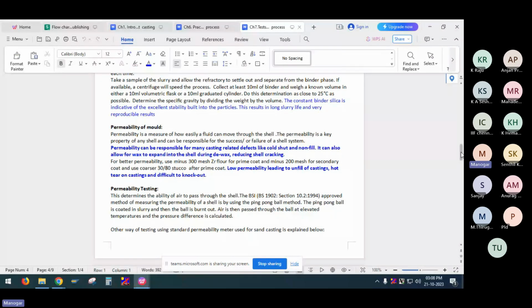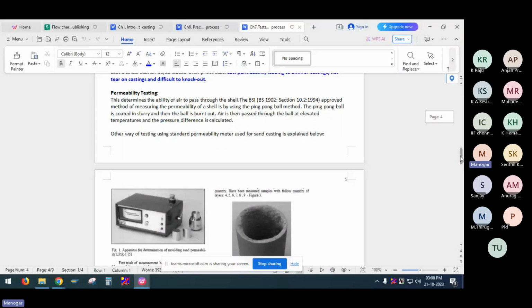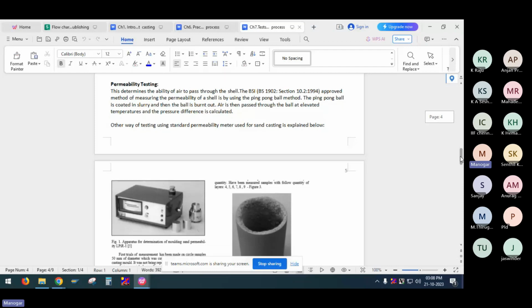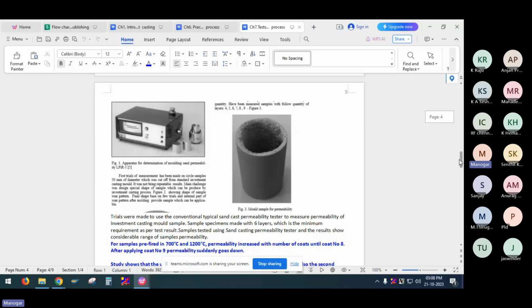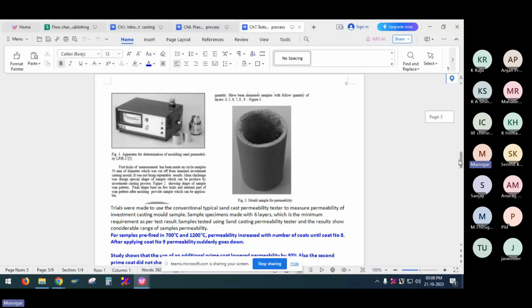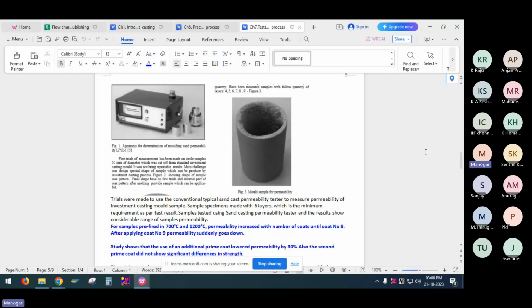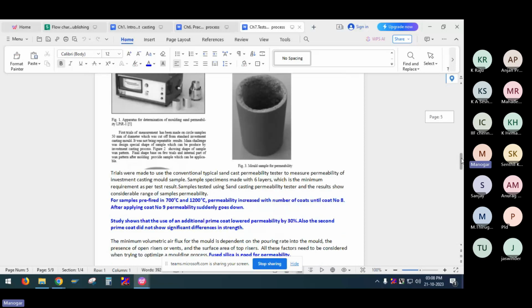Permeability test, there are two ways of measuring the test. That is as per BS 1902, that is using a ping pong ball. The other one is our regular sand casting sample. But in sand casting, you make a circular tube. Here it is a hollow tube made up, as shown in the sketch. The tube is made by coating, and it is tested in the same way as we are testing in sand molds, using this equipment. And this is the test mold sample for permeability. Because many of the countries don't test the permeability, I'm just highlighting that they can practice.